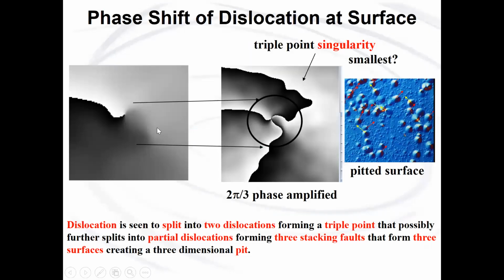Getting back to our specimen, we see this thing that appears like a volume defect. If we phase amplify it by 2 pi divided by 3, we see that the dislocation here, where it's going unstable, actually forms a couple of other dislocations, and there's a triple point right here, which is also a singularity. So one of the questions I ask is, what is the smallest physical singularity? Is it the core of the dislocation, or is it this triple point where the dislocation is splitting into 2 other dislocations?